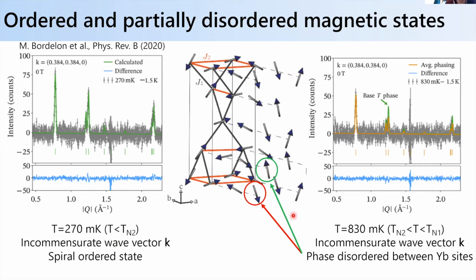But then what happens is when we heat up above TN2 but below TN1, right? So in this intermediate state, this is at 830 millikelvin, then this perfectly ordered state doesn't really fit the diffraction data anymore. And Mitchell came up with a model, the best fit he could come up with, where the relative phasing between these two helices becomes disordered, okay? And so it suggests that there's this interesting intermediate disordered state that's below TN1 before you reach the ground state. So that's kind of an interesting manifestation, potentially driven by fluctuation effects on the ytterbium sublattice.